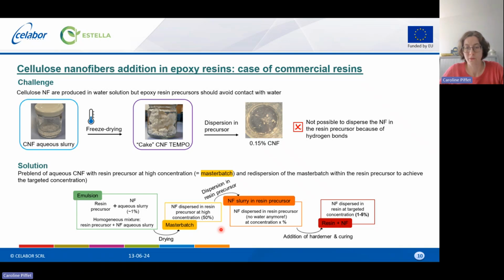We call this the master batch, and this master batch is dispersed into the resin precursor at the concentration we wanted to have it at the end. And then we can add the hardener and proceed to the curing of the resin. And at the end, the goal is to obtain a resin with 1 to 5% of nanofibers.